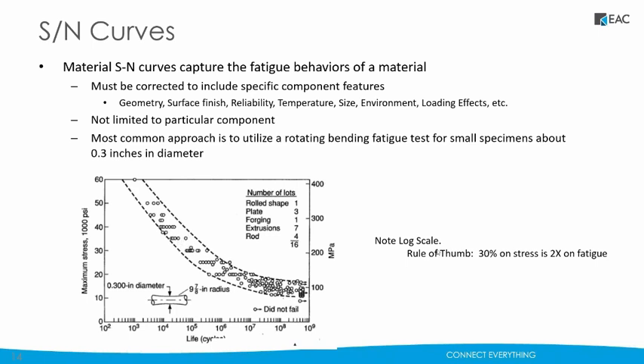Because of the log nature of this scale, I'm going to throw out a rule of thumb that a 30% difference on stress is a 2x difference on fatigue. So if you double the stress, you can have dramatic changes in fatigue life. It's not a direct relationship. This isn't a very good rule of thumb because you're trying to extract a linear relationship from a log scale, but it just drives home the point that even a 15% difference in stress isn't trivial. That can dramatically change your product performance.